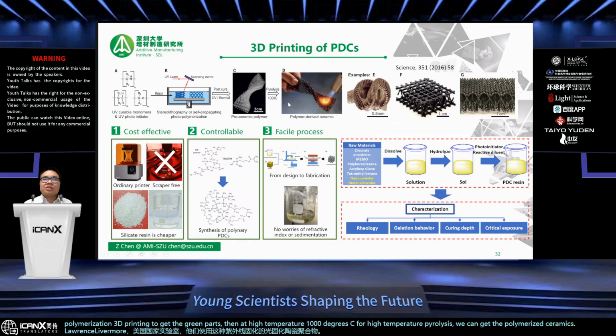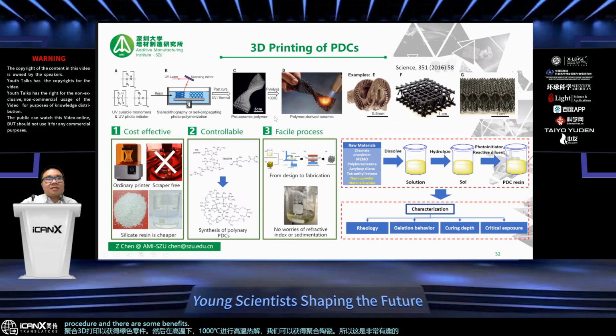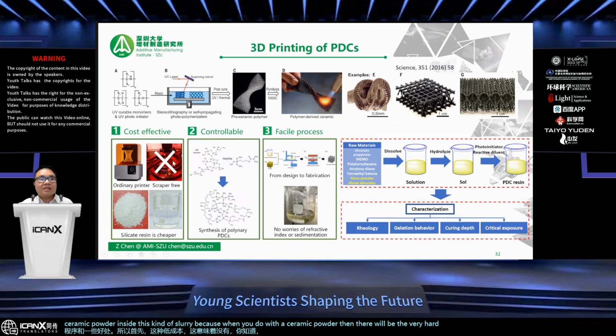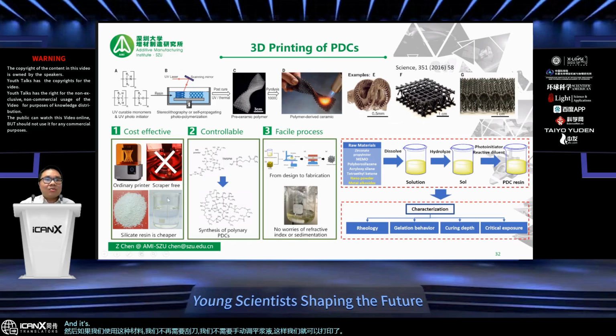So this is a very interesting procedure, and there are some benefits. First of all, there's low cost. It means there's no ceramic powder inside the slurry, because when you work with ceramic powder, it is very hard to level the high viscosity slurry. If you don't level quite well, then the printability becomes lower. If we use this kind of material, we no longer need a scraper. We don't need to manually level the slurry so that we can print, and the inorganic components are soluble, so it will be totally liquid. It's like a resin. This is one of the most important advantages we have.